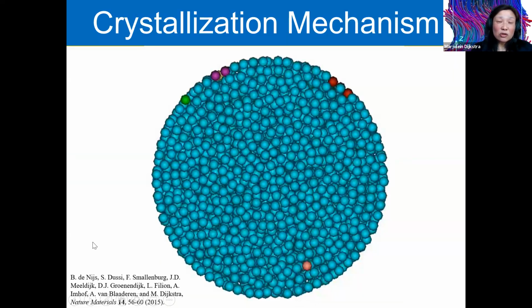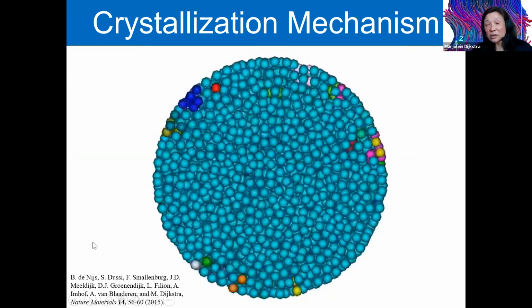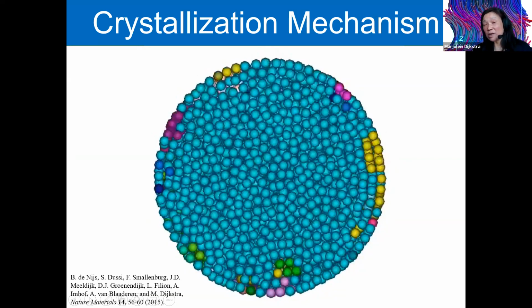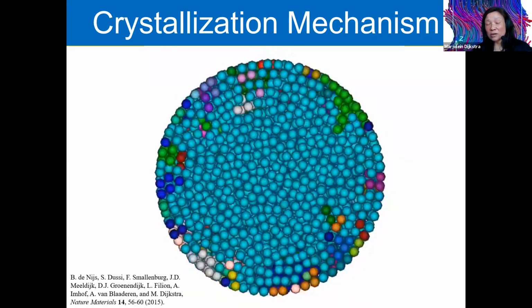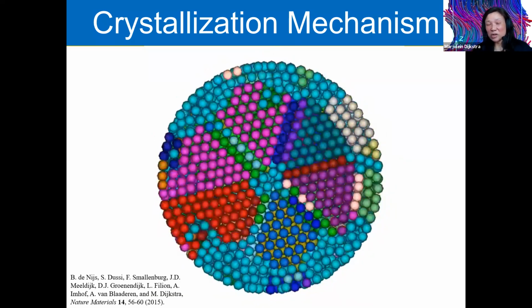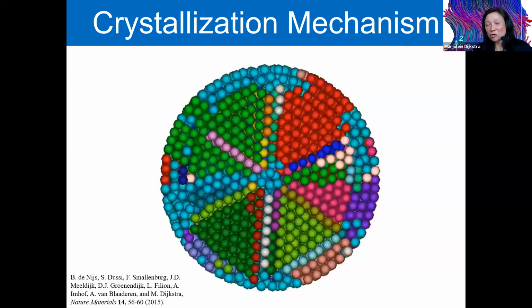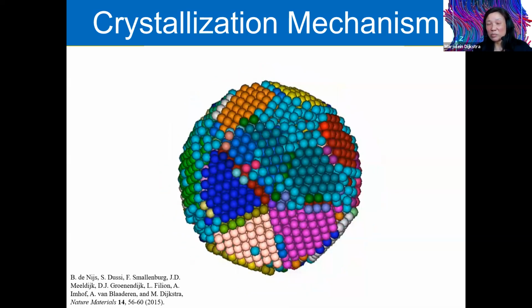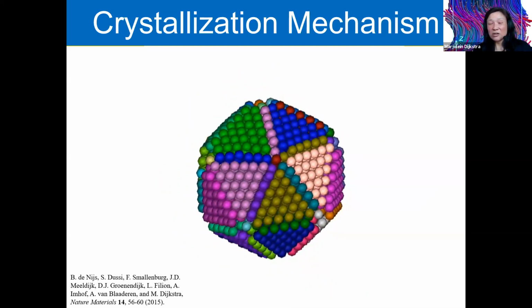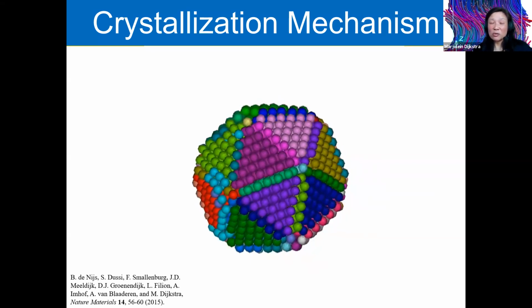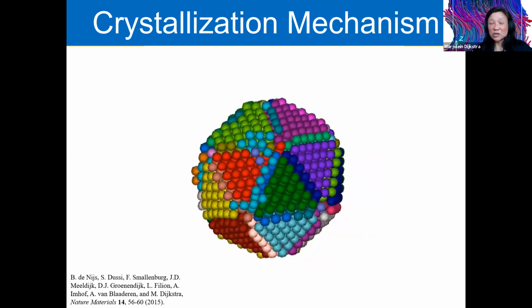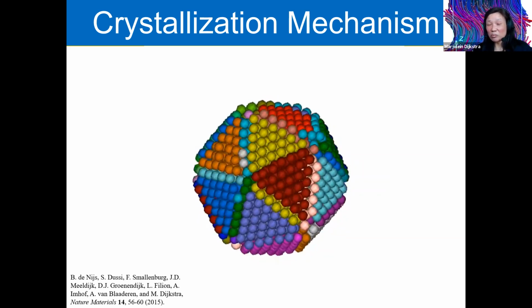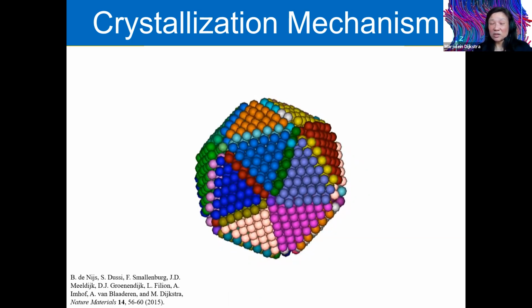So in simulations, we can also look at the crystallization mechanism. One can see immediately that there's a strong layering of the spheres at the surface. The spheres try to self-assemble these tetrahedral domains. If they grow too big, they melt again. If they are not big enough, they grow further. And then in the end, you get this beautiful icosahedral cluster just by putting spheres into a sphere. And this is completely entropy driven. So I find this awesome that it just self-assembles into this icosahedral structure and knows how to assemble 20 of these tetrahedral wedges.